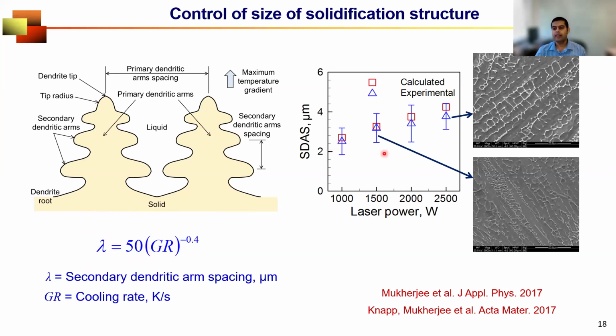spacing. And you see here for different laser power, I show how we can calculate the secondary dendritic arm spacing that is matching with the experiment. For low power, you see smaller dendrites, and for high power, you see larger dendrites, which is very consistent with the calculated results.